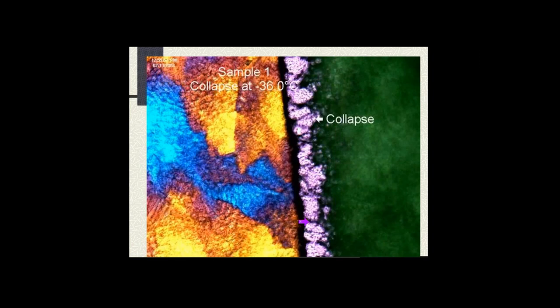Now, there's two temperatures I'm going to be looking at, and I need to put another slide in here. But basically, as we move across here, this is a temperature gradient. We're slowly warming the sample. And right about here, we start to see these tiny little pores open up. And as we get warmer and warmer, we finally collapse the whole structure. This is what I would call the onset of collapse.